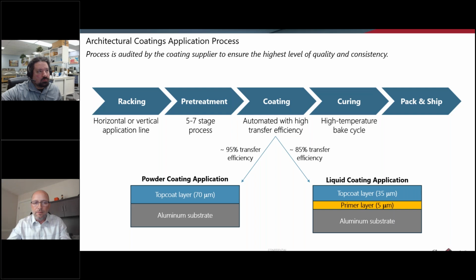Next, you go through the coating process, and that's different depending on whether it's a liquid or a powder coating. But I'm going to stay on this track just to finish that up, and then we'll get into a couple of details on the horizontal versus vertical and the different types of coatings that are used. The coating is applied, and then you go into an oven where the coatings are cured. Whether it's solvent-borne or a powder coating, both of them are baked coatings, so they have to be baked at a relatively high temperature to cure and get the properties to flow out. And finally, those are pulled off of the conveyor belt, packed, and shipped to where they need to go.